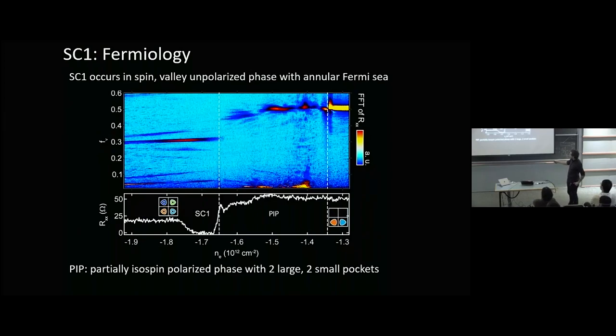This is exactly that Lifshitz situation where you have an annular Fermi sea, and you have a hole-like Fermi surface on the outside, and then you have an electron-like pocket inside. It's all consistent with single particle physics. And then you go into this superconducting state, and then there's a sudden transition to some other state that's broken some symmetry. You see that this is something close to a half metal, but actually it's partially isospin polarized. You have big and small Fermi surfaces that sum up to 1/2. But there seems to be a relatively sudden transition.